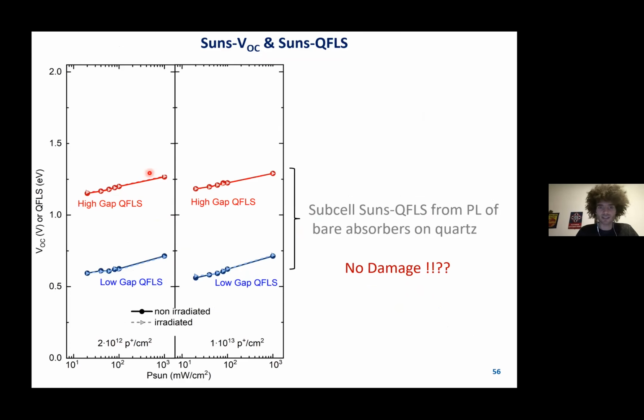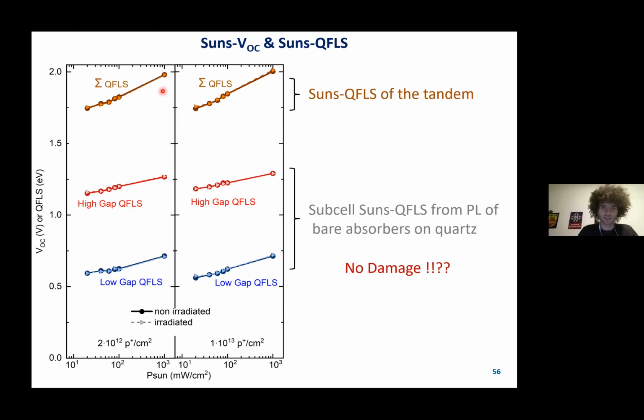So this tells us something about the subcells in the tandem, and these are actually the results from the bare absorbers. So we can now sum the two quasi-Fermi level splittings up to create the sun's quasi-Fermi level splitting graph of the tandem. And again, I observe no damage upon proton irradiation.